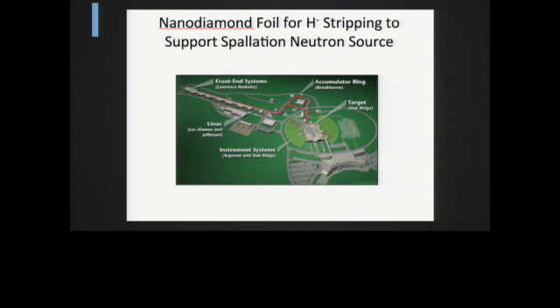One of the things that we've also done is we've tried to take advantage of some of the mechanical properties of the diamond film, and it turns out that this is the neutron source at Oak Ridge National Lab in Tennessee. One of the most important things of this whole neutron source is the ability to create neutrons, and it all depends on this hydrogen stripping technique, where they accelerate a hydrogen beam into a thin film of diamond, and there's an actual reaction that takes place, a collision, and then out comes the neutron. So that thin film has to be able to withstand huge amounts of heat, and diamond is one of the few materials that has the thermal conductivity to do that.